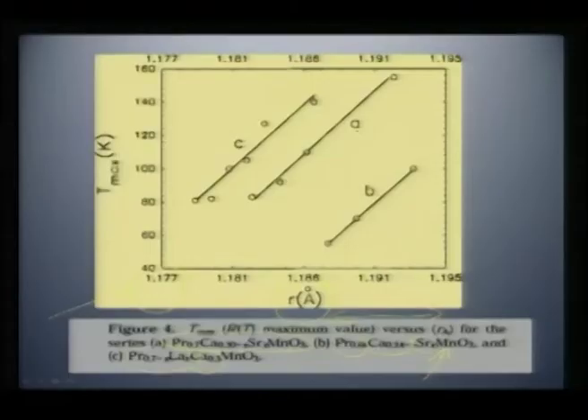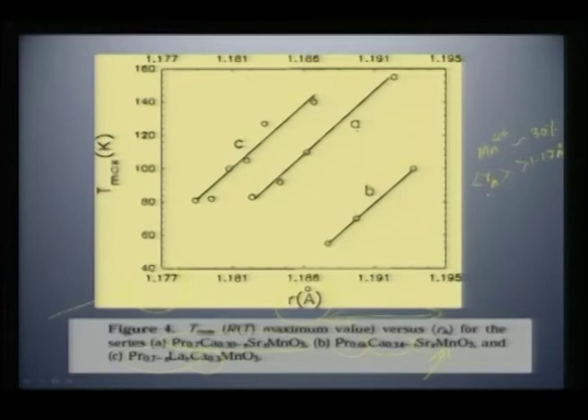So, it is possible when you are trying to make new compositions always to have two things in mind. One is you should always have the Mn4+ ratio approximately 30%, and you should have your average A size value always above 1.17 angstrom. So, you do not even need to do the experiment, you can actually calculate this if you know the ionic size and the valency of your substituting metal, and also the tolerance factor you can calculate, which should be approximately 0.95 or so to keep up with the perovskite phase. So, this is more like a mantra, more like a thumb rule for magnets, that you need to comply with all three to look for a ferromagnetic metal.